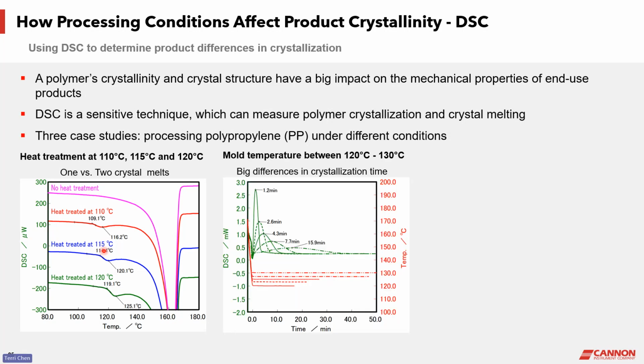The second example shows how much molding temperature could impact the polymer's crystallization rate. From these DSC isothermal test results, we can see that if we set the mold temperature at 120 degrees C, the polymer's crystallization peak is observed at 1.2 minutes. But if we increase the mold temperature by 10 degrees, it significantly slows down the crystallization rate. The peak of the crystallization is observed at almost 16 minutes.